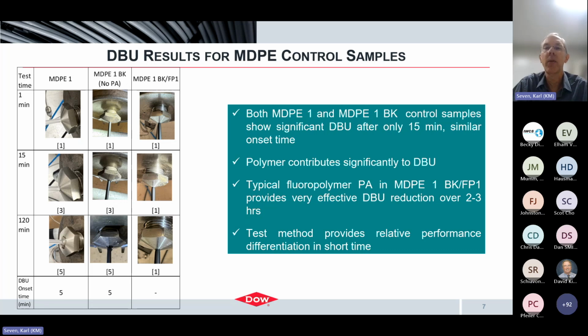MDPE1 was a control sample or comparative sample. So basically just the polymer itself. And so in that series of pictures, you can see that the buildup occurs quite rapidly with the onset occurring within 5 minutes. And overall, there was quite severe buildup at the 120 minute with a rating of 5.